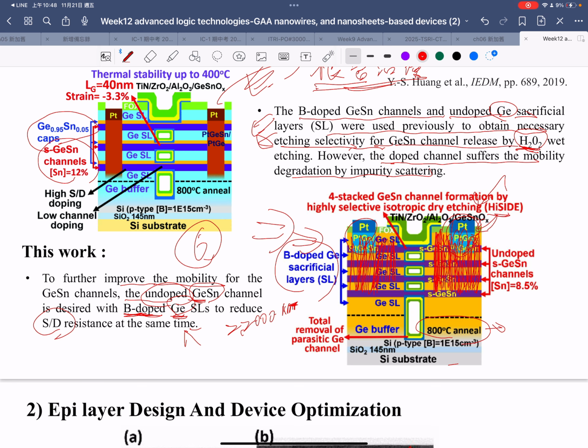Actually, a long time ago, I saw the TEM picture for this. I think you know the differences between with and without the 800 degrees Celsius anneal process. The dislocation density could be suppressed a lot after the 800 degrees Celsius anneal process. And then actually we will have a parasitic germanium channel here, because in TSRI we just have a gate-first process flow. So we will have a parasitic germanium channel, which will cause some problem. So this is a problem.